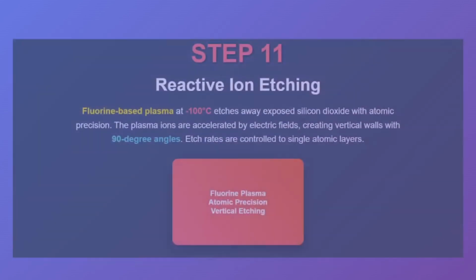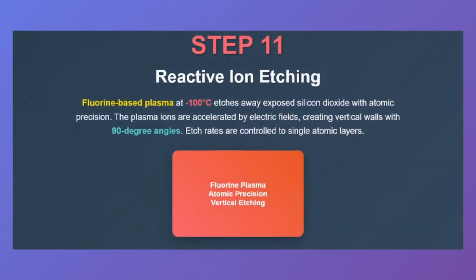Step 11. Reactive ion etching. The revealed areas are etched away using a plasma of fluorine ions at sub-zero temperatures. The process creates straight, vertical trenches with atomic precision. Every layer must be etched with nanometer accuracy.